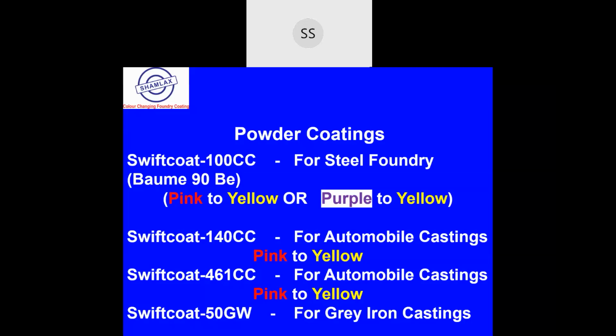Pink to yellow coating will be suitable for the alpha set sand system. You can have it for the resin coated sand system or even for the cold box sand systems. Purple to yellow will be suitable for the phenolic sand system and for the phenolic ester cured sand systems. Swift coat 140 cc will be pink to yellow, suitable for the automobile castings.